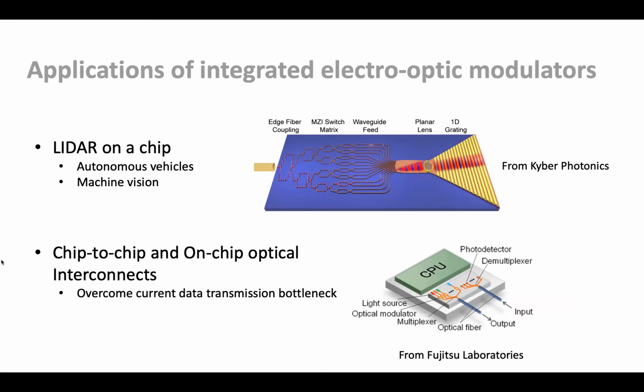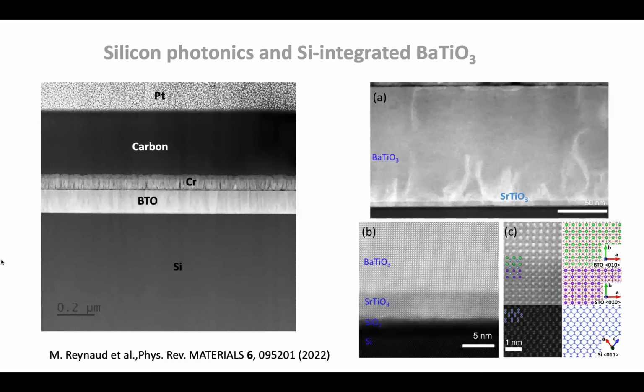So this is why I want to do this. I want to build an electro-optical modulator, except my material doesn't look nearly as pretty as I wish it would. It looks okay on this scale. This is 0.2 microns, so it's a nice barium titanate on silicon. And I want to do all that within silicon photonics because they have a manufacturing infrastructure, right? Now, if you zoom in, this is now 5 nanometers. Our dislocation looks kind of ugly.